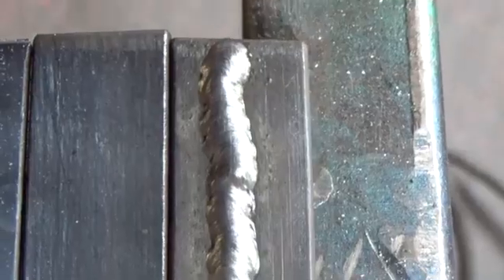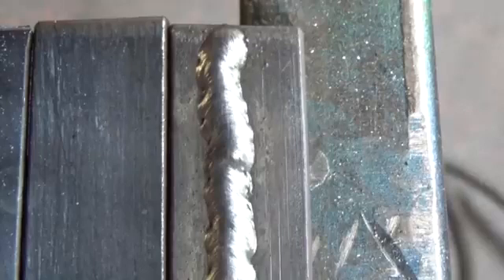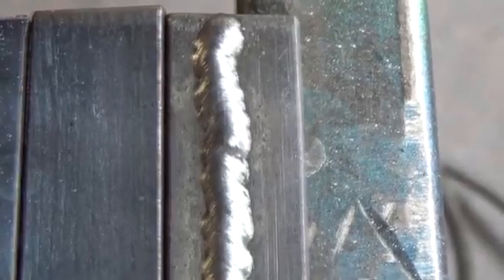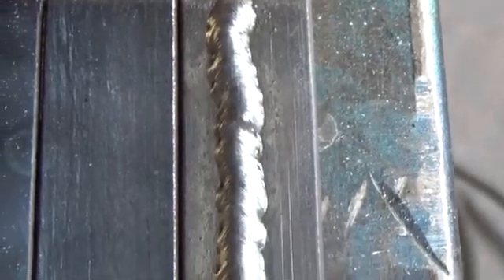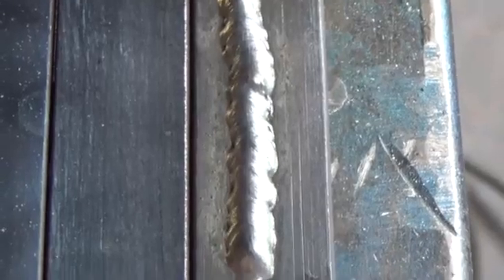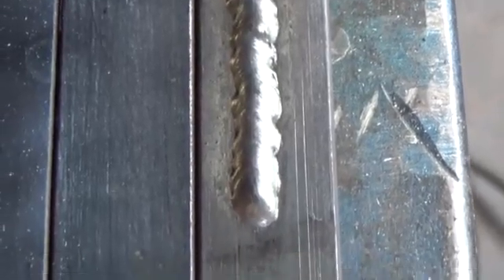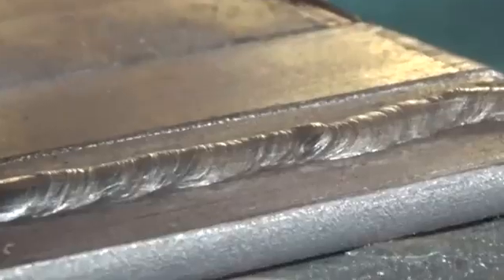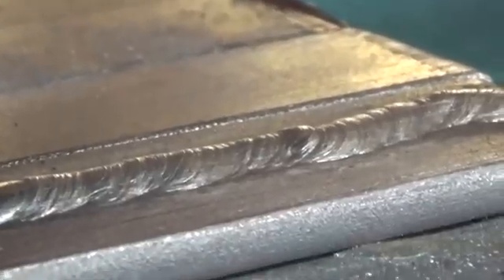The form of the seam is incorrect. It is too narrow and high. On the border between the weld and the base metal, dark spots, small holes, are clearly visible. That means poor fusion between the weld and the base metal. In cross-section, an acute weld is visible. Let's do the next weld.